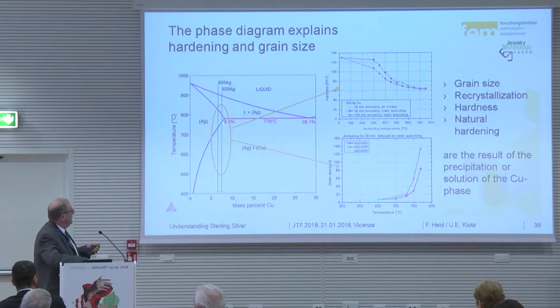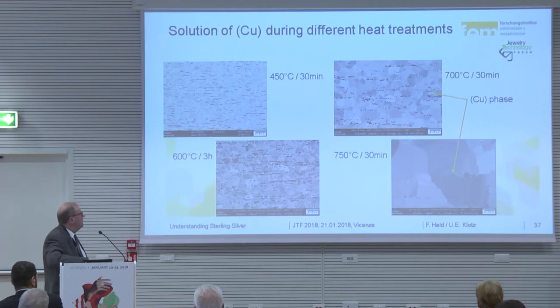Here we have 925, we have 935. Here the temperature, and this is the solid solution of copper in silver, which increases with higher temperature. And this is what we have talked about: grain size, recrystallization, hardness, natural hardening, it's here. Here it's the grain size, you see, if we anneal in this temperature range, there is no grain growing. Only if we have no copper phase in it, the grain growing starts. Here again, the solution of copper during different heat treatments. 450, 600, 700, and if we make a high annealing, we have no copper, and then we have the real grain growing.